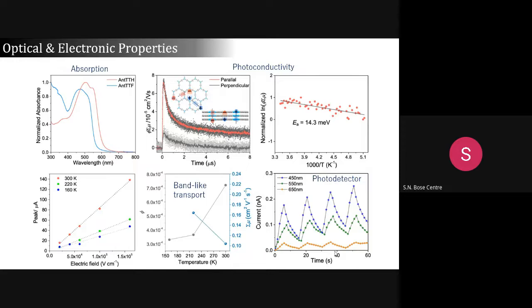And we did the temperature-dependent time-resolved microwave conductivity, and we can see the activation energy is almost 14.3 meV. As you know, the thermal energy at room temperature is almost 25.6 meV. So this exciton can break into charge carriers even with a very low binding energy. This plot shows that different temperatures affect the conductivity to a different extent.